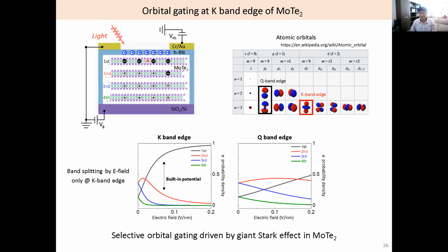In the top hBN device, we have some uncontrolled impurity charges, plus, plus, plus. Of course, some people say hBN is really, really clean. This is from NIMS in Japan. But still, their hBN also contains some defects and impurity charges. And by the impurity charges, some electrons are accumulated here at the top MoTe2, and screening behavior, Thomas Fermi screening, happens here.